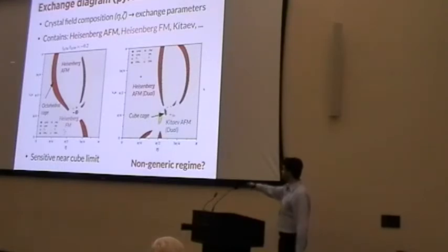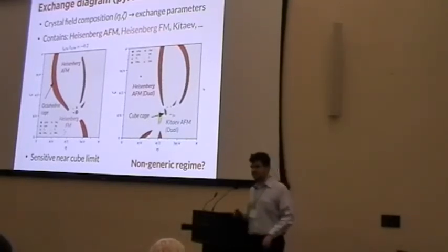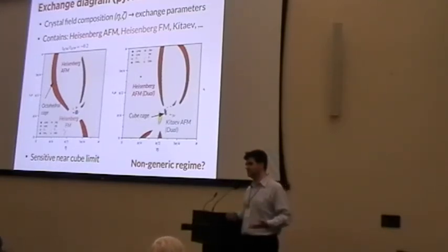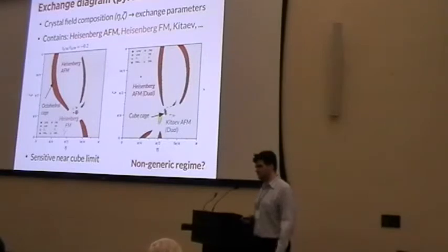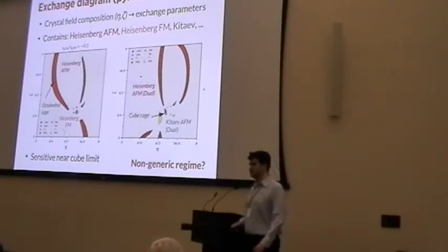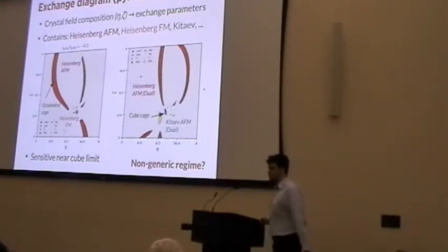Yeah, so again, this is material dependent because it depends on the crystal field and exactly what that implies about the doublet. But one might say, for example, the spinels, I wouldn't expect it to be too far from here. Making that quantitative is difficult because the crystal field, for example, doing a simple point charge calculation is not quantitative for these systems. So you have to fit it from experiment, and for terbium, it's not clear there's enough data in the levels to do that.